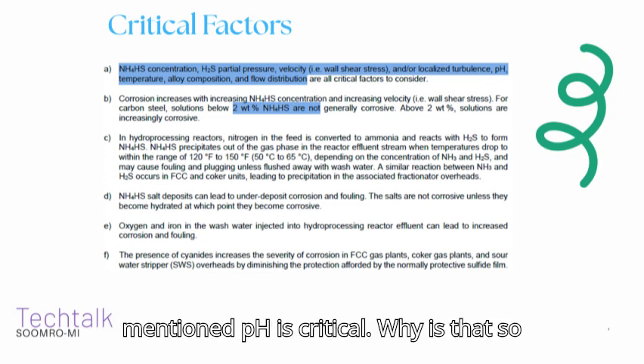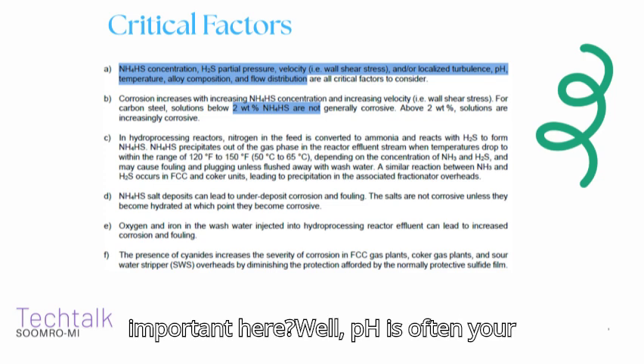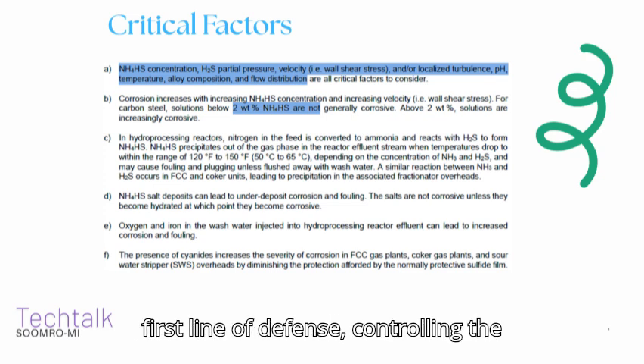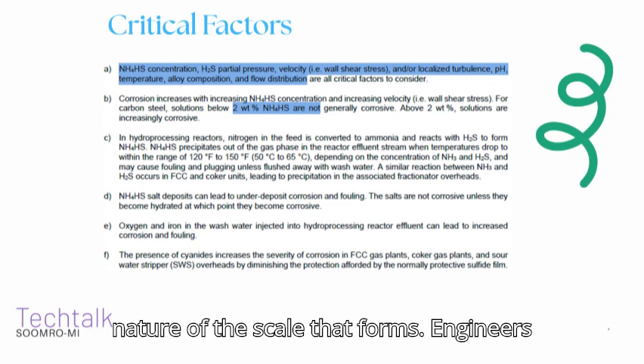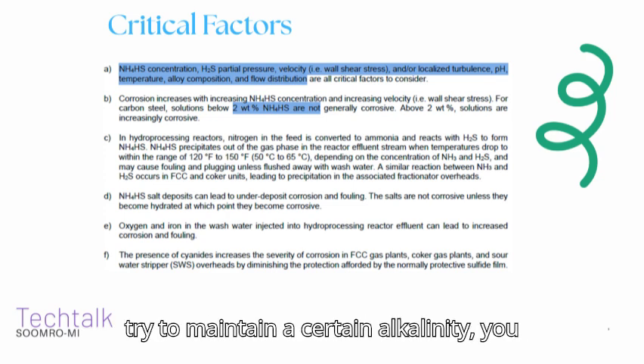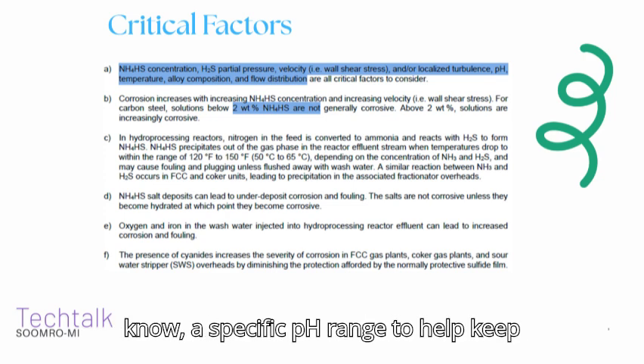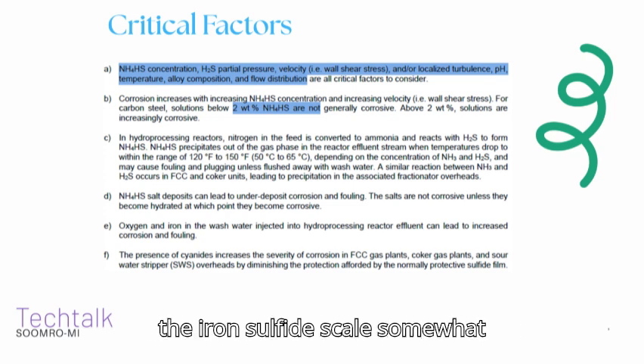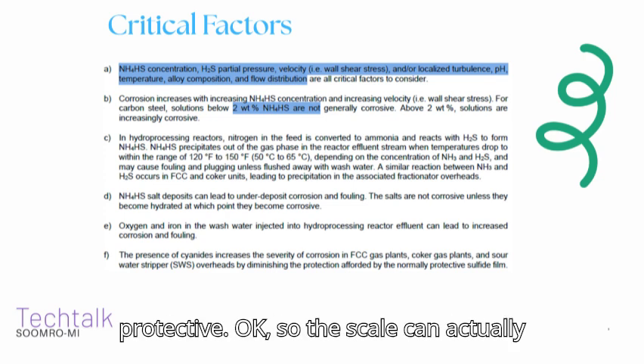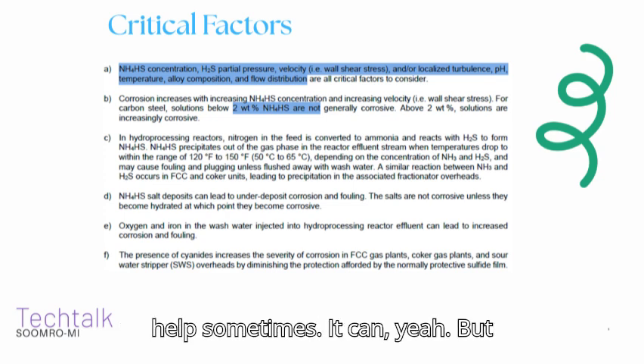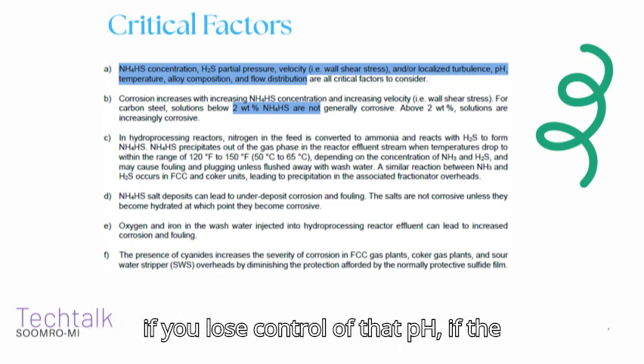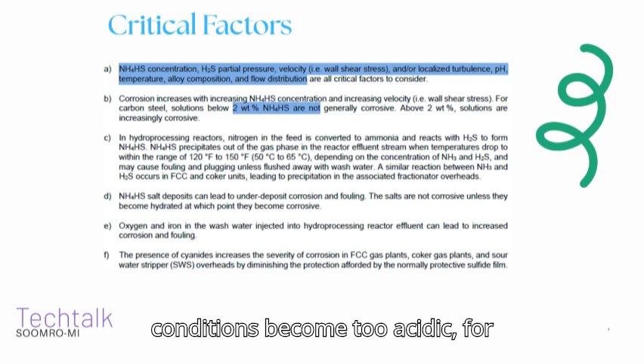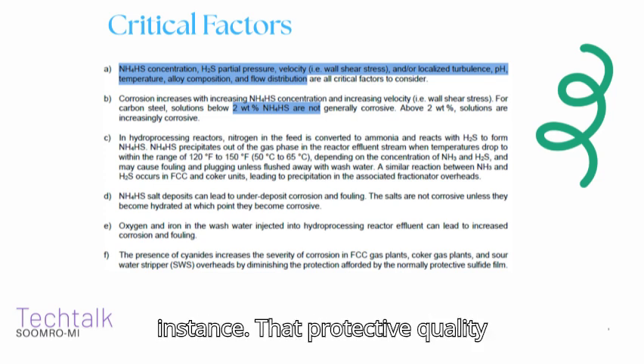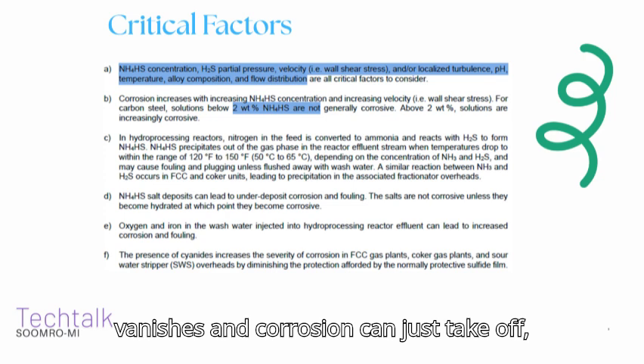You mentioned pH is critical. Why is that so important here? Well, pH is often your first line of defense, controlling the nature of the scale that forms. Engineers try to maintain a certain alkalinity, a specific pH range, to help keep the iron sulfide scale somewhat protective. Okay, so the scale can actually help sometimes. It can, yeah. But if you lose control of that pH, if the conditions become too acidic, for instance, that protective quality vanishes and corrosion can just take off.